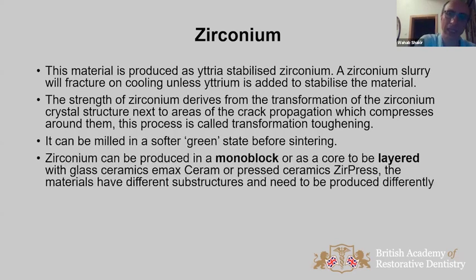It can be milled just like Emax can. Going back to it, you can mill your Emax into a green state first, and then adjust it, check it, and then sinter it. Same with zirconium. It can be milled into a softer green state just because it's a bit easier to adjust. Once it's fully formed and fully fired, it's quite difficult to adjust those things, as you probably know. When you try to adjust a zirconium monoblock crown, sparks fly off, and so you can see how careful you have to be with it.